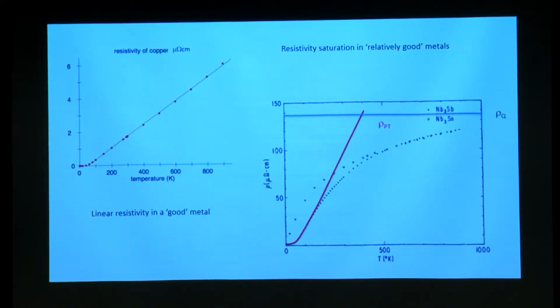Now, there are not so good metals. Examples are these, niobium-tin and niobium-3 antimonide. Here you see that the resistivity is sort of linear somewhere, but then it begins to show signs of saturation. Here the resistivities are rather large, much larger than here, 50, 100, 150 micro-ohm centimeter. So good metals: resistivity low but linear. Bad metals: resistivity has a linear regime, but signs of saturation.